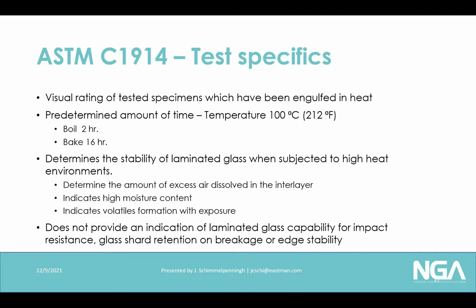Couple things that it does is it determines if there's a large amount of excess air or moisture that gets trapped in the interlayer and can cause issues. It's a good indicator of high moisture content. And it also can indicate if volatiles are formed with exposure. So say there may be some polymer degradation. You may see that you have boil or bake failures when they come back after exposure. One thing that the boil and bake test doesn't do is it doesn't provide an indication of laminated glass being capable of impact resistance, glass shard retention, or anything like that on breakage or the edge stability. It truly is a durability